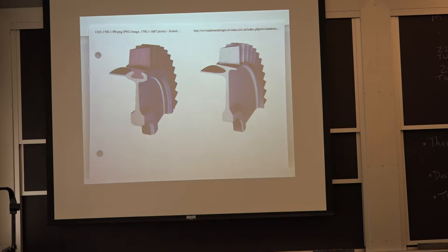Blades today, this is a 30, 40-year-old blade design, but blades today are even fancier. They'd like to make them thinner and thinner. They're down to about 7 to 10 thousandths wall. And the problem is, you have a ceramic core inside this thing that you cast around, and you grow the single crystal very slowly. If it shifts by 1 or 2 thousandths of an inch, you've got junk because you can't afford 2 thousandths of an inch out of 7 thousandths. Okay, so you really can't get them any thinner than they're already making them. So they've gone about as far as they can with cooling.